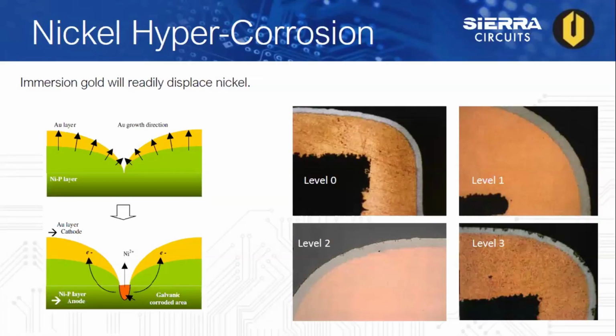On the right-hand side, there are several corrosion ratings categorized by IPC 4552B. We start with level 0, categorized as defect-free—there's no nickel corrosion spikes, and it looks pretty smooth, as you can see in the image. Level 1 is when there are a number of defect spikes, less than 10 in quantity, and the spike depths are no more than 20% of the nickel deposit thickness.